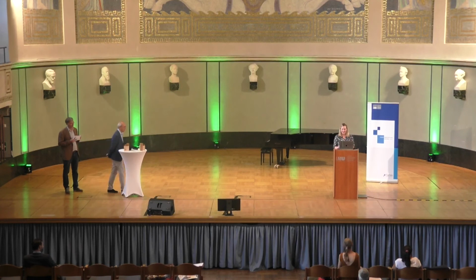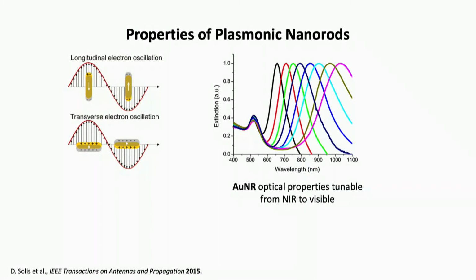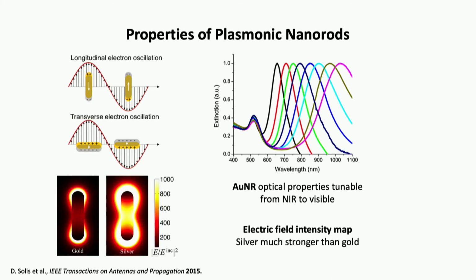Okay, I'll do a quick run through of why we use these gold-silver core shell nanorods in lateral flow assays. Nanorods are very cool because they have really distinct optical properties, and you can tune them all the way from the near infrared to the visible. Quite often it's gold nanoparticles that are used, albeit them having less optimal optical properties compared to silver. If you look here at these electrical field intensity maps, you can see that silver is much stronger compared to gold. So why don't we use silver?